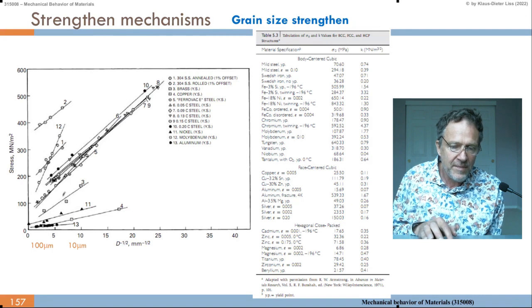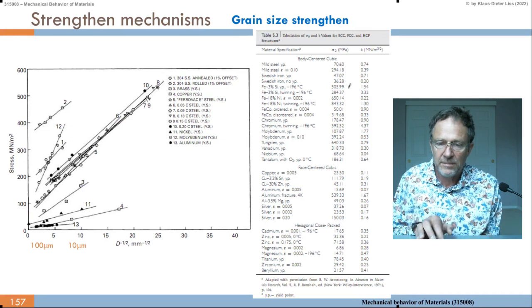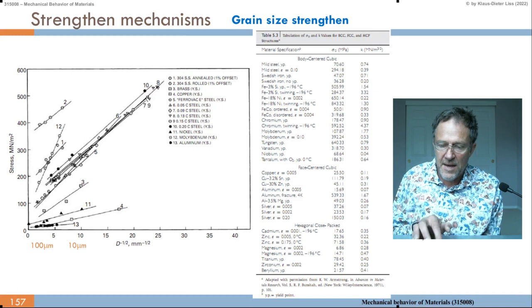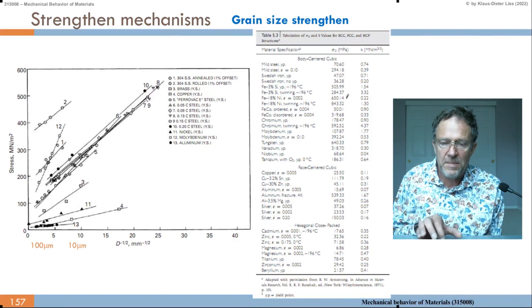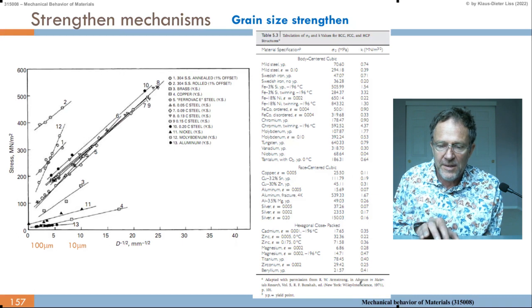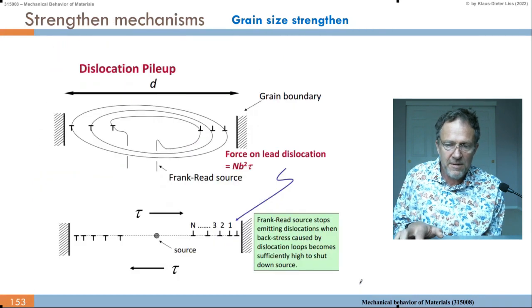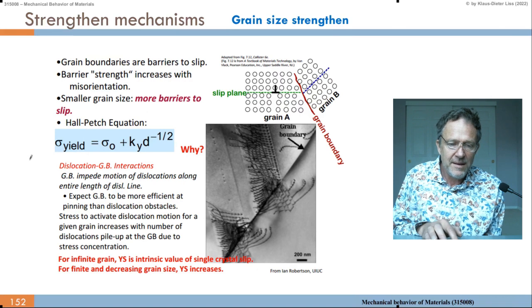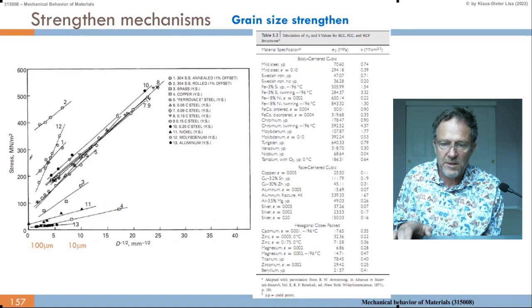Brass number 3 is there, so brass is much softer. Copper number 4, copper is very soft, we know that, particularly when it's annealed, but it behaves well, the Hall-Petch behavior. So there are tables when you design a workpiece and when you design a microstructure for making a workpiece. Then you have the sigma zeros here given in megapascal for all of these materials, and the K. So typically the K, the K_Y as we call it, is shown there. So you can put it into this Hall-Petch equation and get the yield strength as a function of grain size.